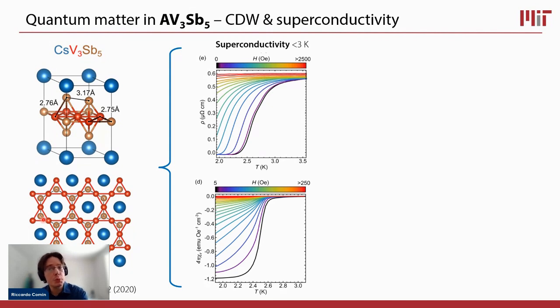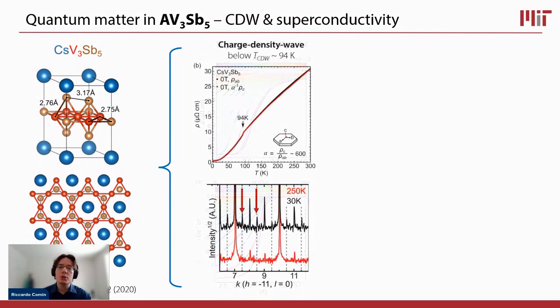This material exhibits superconductivity at a relatively low temperature of around 3 Kelvin. And it also exhibits what's known as a charge density wave below a temperature which is a bit higher, of order 94 Kelvin. And the charge density wave can be seen in transport. So you see an anomaly in the resistivity, and that signals some kind of symmetry breaking transition, in this case, the charge density wave. But it can also be seen in diffraction. So you can probe it directly in reciprocal space in the Fourier domain. So the charge density wave phase manifests itself through the appearance of some superlattice peaks in the diffractograms of the material.